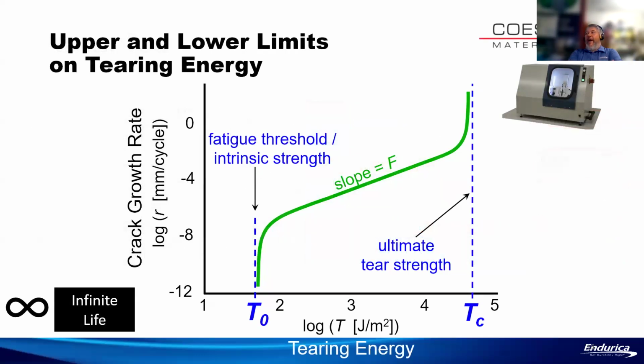So, like I say, rubber has a fatigue limit, and what you're looking at in this plot is the crack growth rate curve for rubber. You can see that on the x-axis, we're plotting the energy release rate, or some people call it the tearing energy of rubber. This is the intensity of the load; the stress or the strain is related to this. And you can see that there's a critical value of TC, and if you exceed that, the part ruptures. It's a strength problem. If you decrease the tearing energy input, the rate of crack growth gets slower and slower and slower. Eventually, as you reach this limit T naught, the crack growth rate will actually drop to zero.